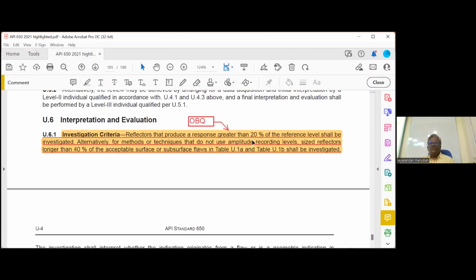Reflectors that produce a response greater than 20% of the reference level shall be investigated. Alternatively, for methods or techniques that do not use amplitude recording, reflectors longer than 40% shall be investigated. That is an open book question.